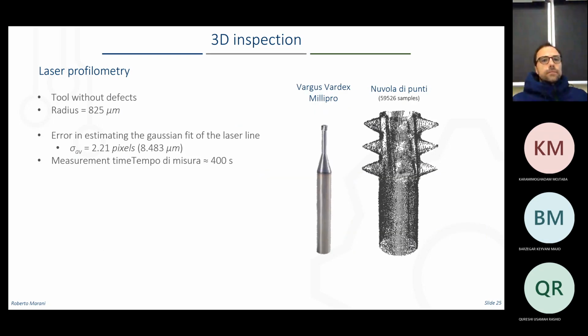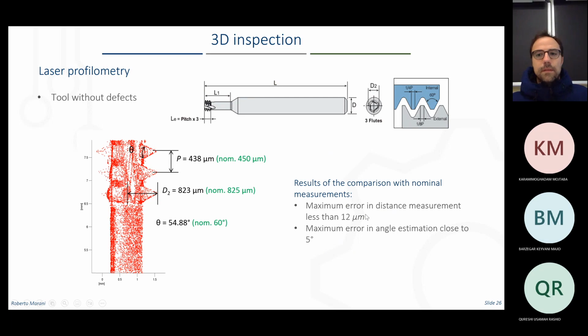And then, for example, in this case, there was an error in estimating the Gaussian fit, that is, let's say, the standard deviation of this profile, that was 2.21 pixels. Everything is at sub-pixel scale, because we can also use decimals, even if we are working with indices. And there are many measurements that we can run, and this was just to show you the resolution that we can get in the distance measurement. Of course, in any case, these are visual measurements done with light.